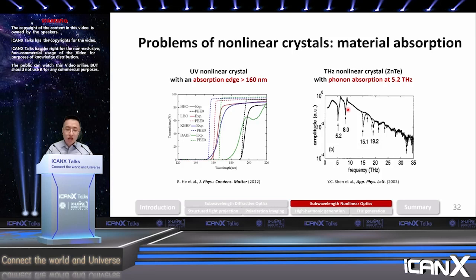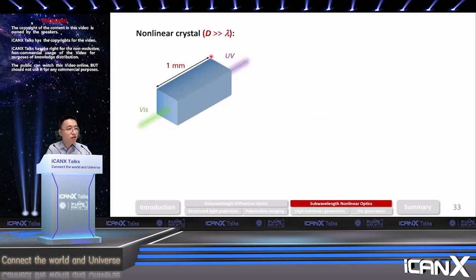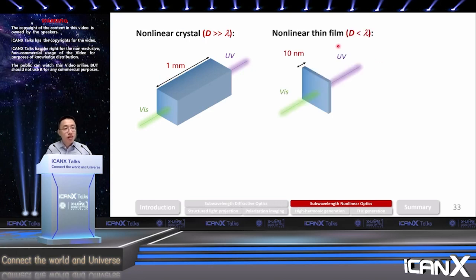In order to address these two problems, we see that most of the time our nonlinear crystals have a thickness much greater than the wavelength of light, on the order of, let's say, 1 millimeter or 1 centimeter. What if we create a nonlinear thin film with a thickness smaller than the wavelength of light, let's say about 10 nanometers? Upon first look, you might see that it is one stone, two birds: you'll solve both of these two problems here.